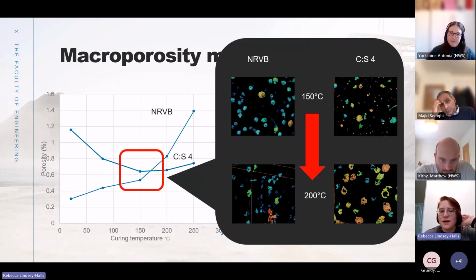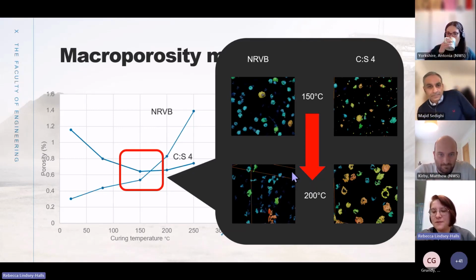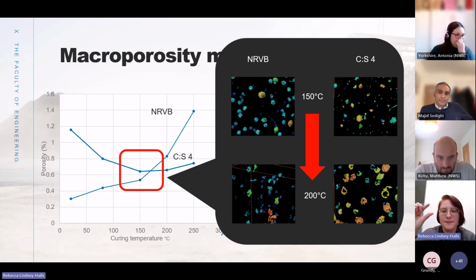So these are the XCT scans from 150 and 200 degrees. Which I think is quite interesting because as you can see, there's a change in the pore shape. At 150 degrees, they're more spherical, which is what you imagine when you think of a pore. Well, I do anyway. But when you increase the temperature to 200 degrees, the NRVB samples are more horseshoe shaped, whereas the higher silica addition samples are a donut shape. I think this is interesting because you are also changing the mineralogy.